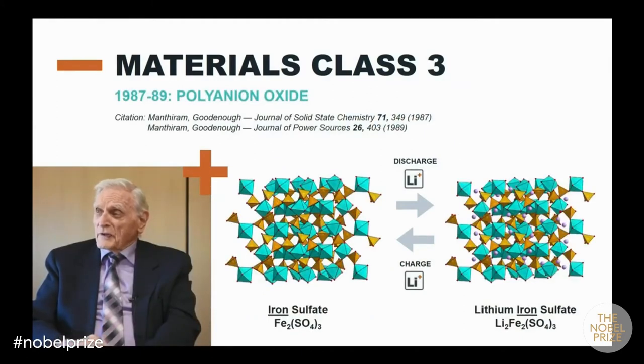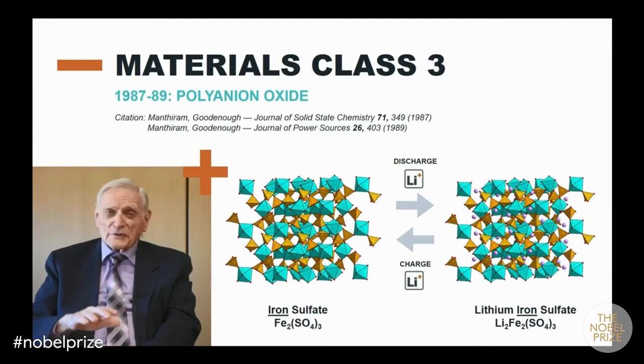There is a so-called inductive effect in which you get a very strong sulfur-oxygen bond in the sulfate, and that is able to reduce the energy of the iron 3+/iron 2+ redox couple. And so I wanted to get a higher voltage, and so I wanted to lower the energy of the iron 3+/iron 2+ redox couple. And so you go to a sulfate. The sulfur has a strong sulfur-oxygen bond, and that then makes you have a more ionic bond with the iron, and lowers the energy of the iron 3+/2+ couple and increases the voltage.